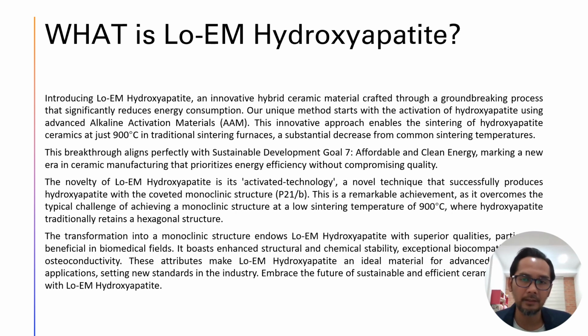So basically, the Lo-EM hydroxyapatite is an innovative hybrid ceramic material crafted through a groundbreaking process that significantly reduces energy consumption. This unique method starts with the activation of hydroxyapatite. This is the recipe, basically the secret trait, using the advanced alkaline activation materials, AAM. We use metakaolin as a precursor for this project. This innovative approach enables the sintering of hydroxyapatite ceramic at just as low as 900 degrees Celsius, where traditionally it should be sintered within a temperature of 1100 to 1600 degrees Celsius using the conventional furnace.